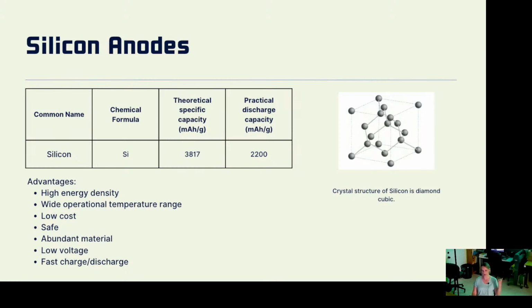And there's so many advantages. Like, it's also low cost, it's also low voltage, it's abundant. And what's interesting about silicon is, instead of, like, you've seen all these materials, the lithium inserts itself into the crystal structure. Silicon actually alloys with lithium, and it turns the crystalline silicon amorphous. It's no longer crystalline. Really interesting process.